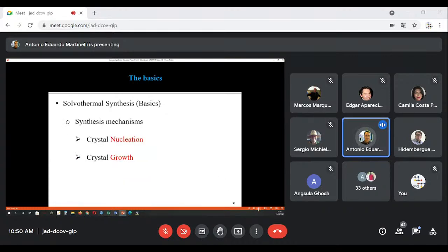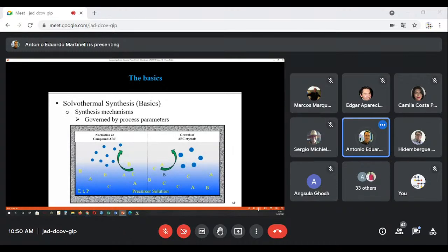The main synthesis mechanisms involved in the solvothermal synthesis are crystal nucleation and crystal growth, and this is what we see in this slide. If we look on the left side, we see the convective mass transfer of the species that make up the precursor solution to regions where the species combine in a stoichiometric ratio, starting the nucleation of small crystals, here named ABC. If we look on the right side, now we see mass transfer of dissolved species to the surface of existing crystals, promoting their growth.